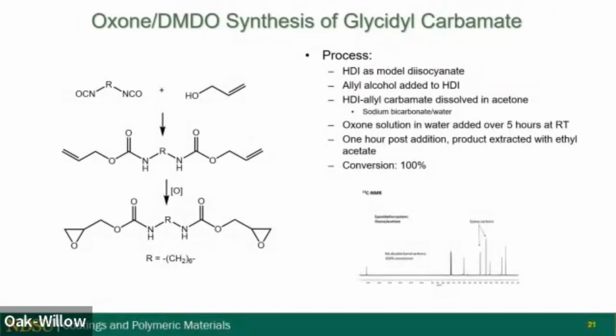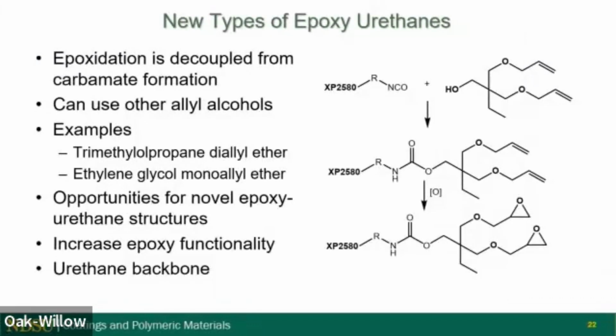And it's very efficient, the NMR, carbon-13 NMR here. We would see peaks here if we hadn't fully epoxidized the system. So again, 100% conversion, very safe reagents, done at room temperature. And so again, that was a very good outcome of that.